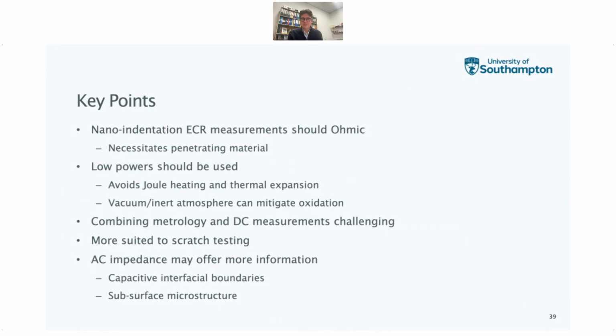It's challenging to combine metrology with these sorts of direct current measurements for those reasons, because you necessarily need a low contact load to avoid damaging the surface for your metrology, but actually for trying to get the resistance measurements, this isn't necessarily conducive. So we think probably this is more pertinent to scratch testing, but obviously we need to work out those contact areas as well.